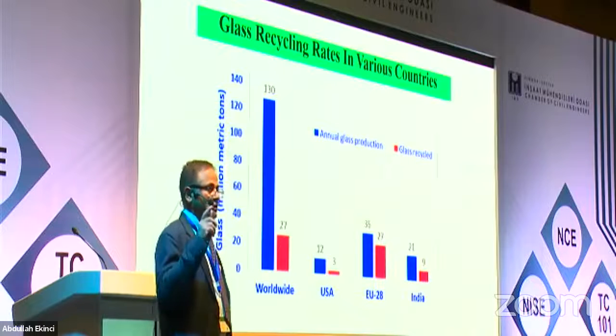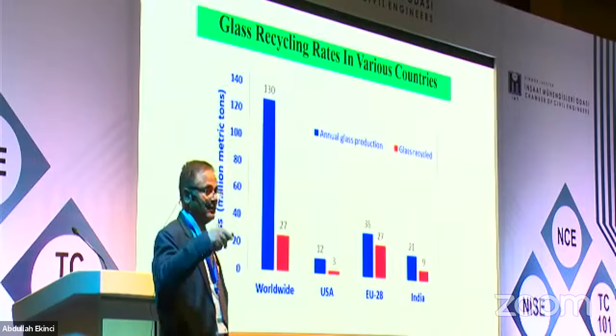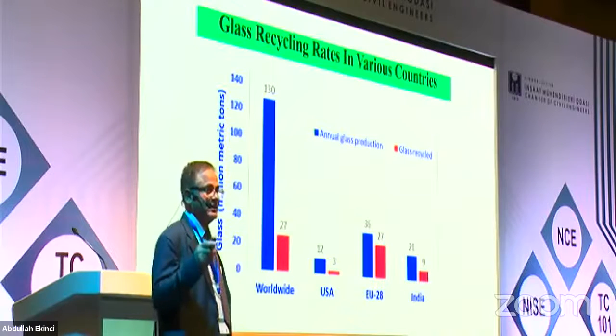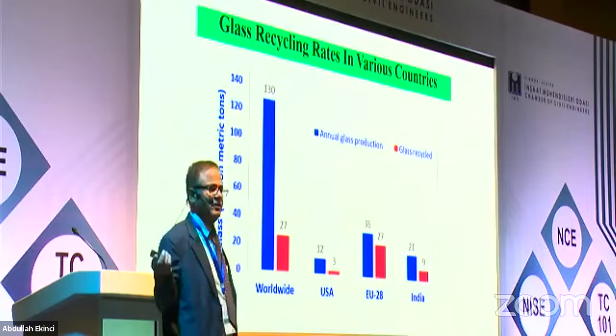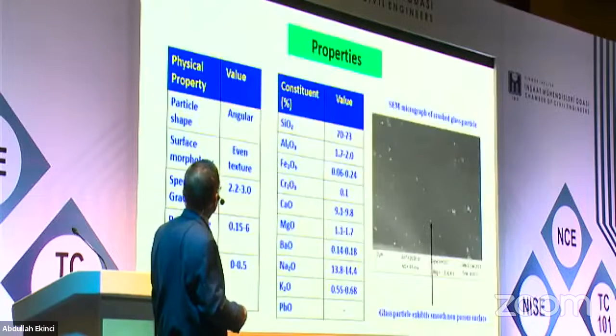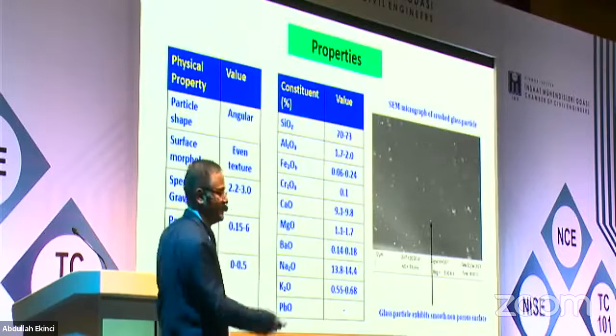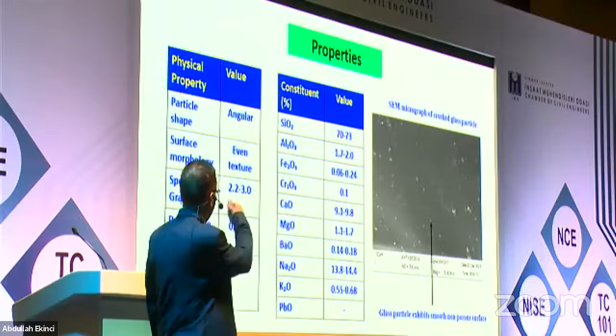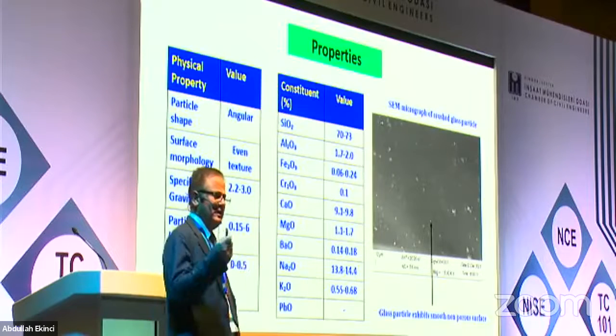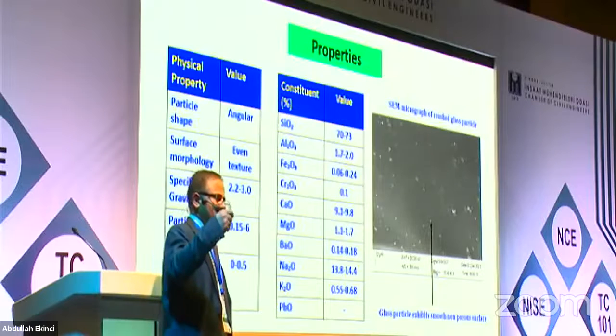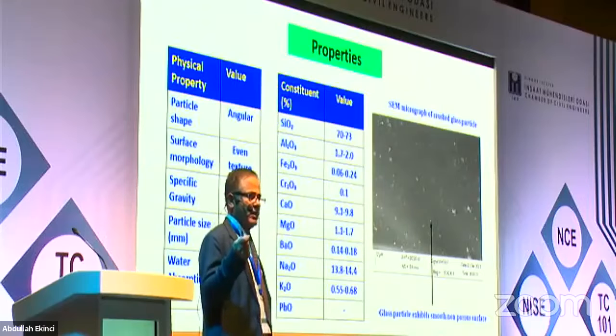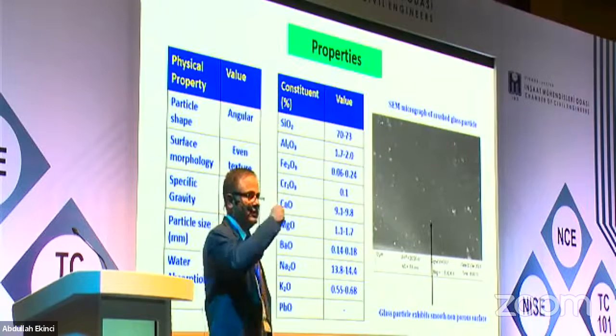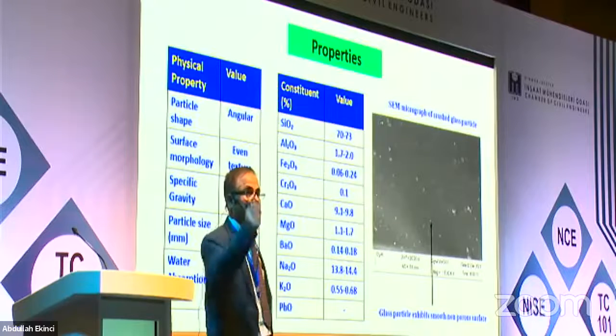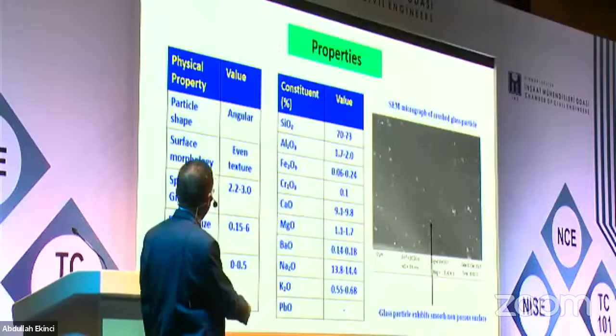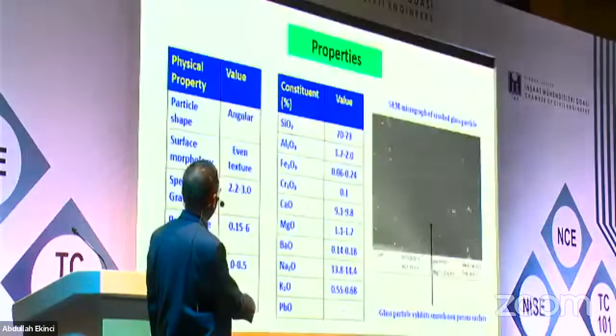But with a caution, you need to be careful in grinding to the proper size. If it is irregular in size, instead of helping, you may not achieve good strength for structural concrete. Otherwise, for lower grade concrete, there is no problem. So this is how particle shape and particle size matter, for the benefit of the audience. It is high in silica, but it also has calcium oxide, silicon oxide, ferric oxide. To be very honest, once the ASR problem is fully solved, it could be a wonderful material to be used along with silica fume and fly ash for high performance concrete, because it has a decent amount of calcium oxide, aluminum oxide, etc.